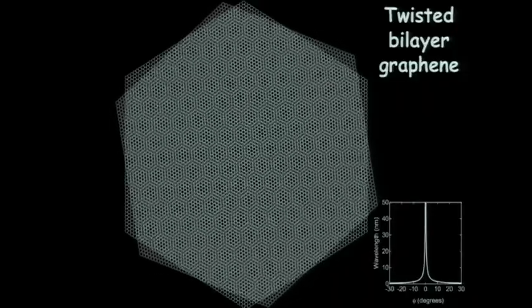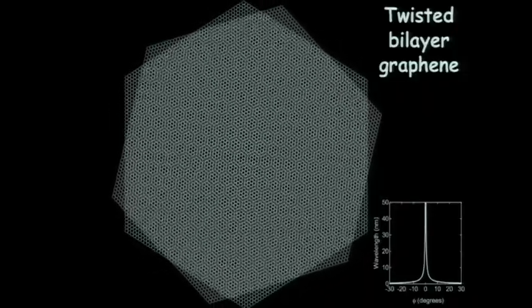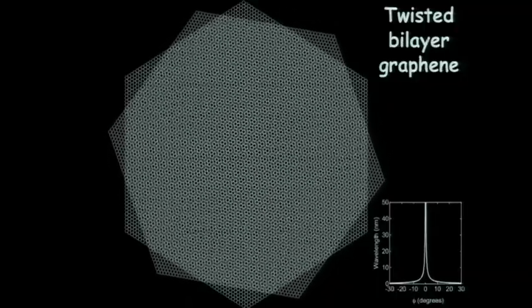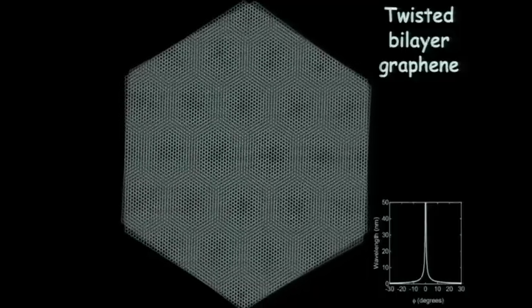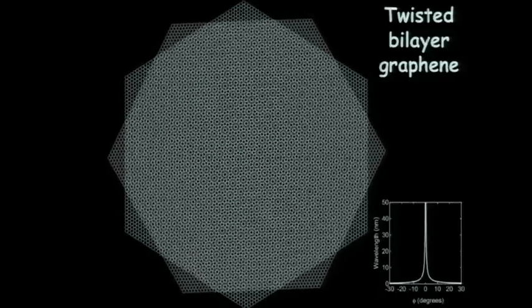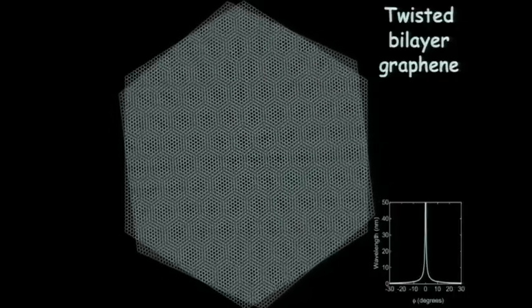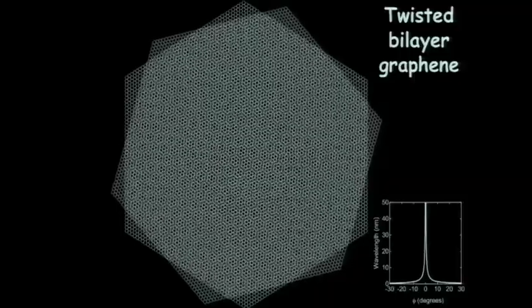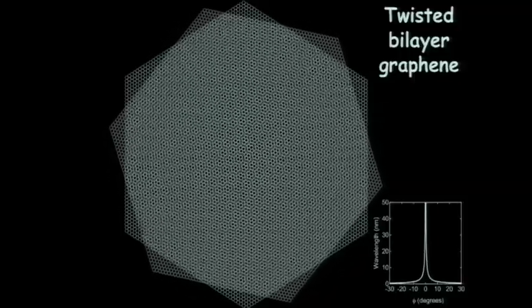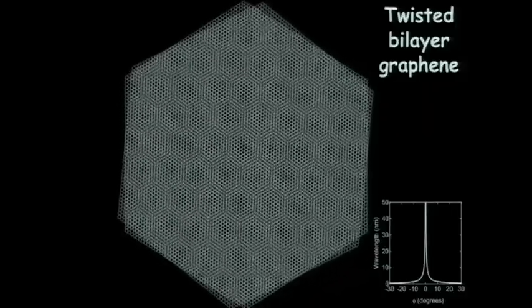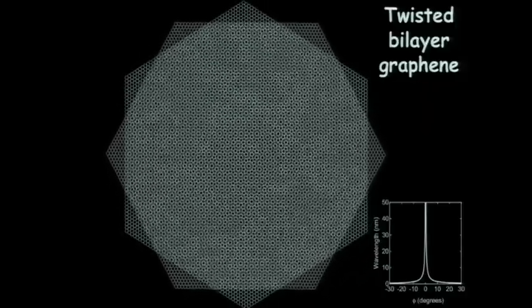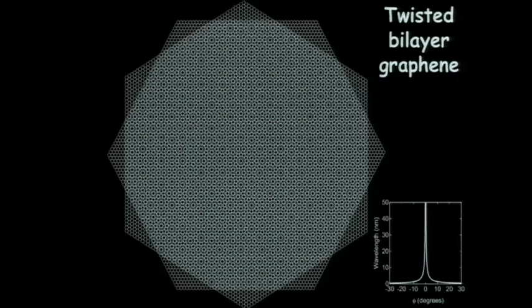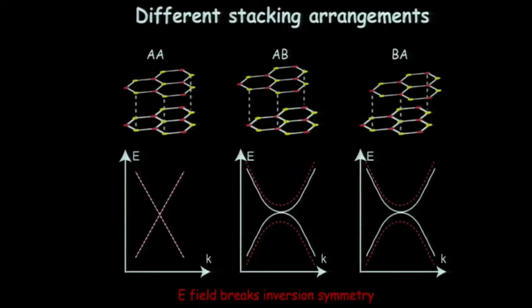And so here, if you look, there's a slight difference to what happens when you twist them. So before you saw when they twist it, the whole pattern kind of rotated with twist angle. This one just goes in and out. And so the orientation of the Moiré pattern with respect to the graphene lattice is very different in this case of graphene on graphene than it is on graphene on boron nitride. And so you can see here as it gets very long, it stays aligned with the graphene lattice here. And so when that's happening, there are going to be regions in this long wavelength Moiré pattern which have AA stacking. So the 2 lattices directly on top of each other. There's going to be regions which are Bernal stacked, AB, and also BA here.